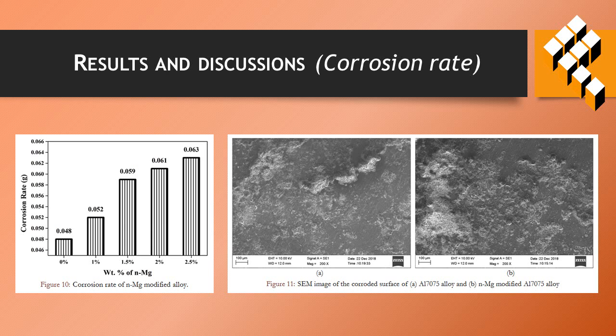Figure 10 shows the corrosion rate of the nanomagnesium modified alloy. Here, due to the reaction of magnesium particulates, a high corrosion rate was found in the modified alloy. From the same image, it can also be observed that the base material corroded very little compared to the nanomagnesium modified alloy.